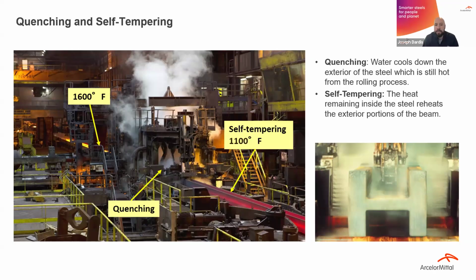So you can see it leaving the QST bank in that picture on the left, and it's dark all around that piece of steel. A few seconds later, it starts to glow orangish again. So what's happening is the heat retained within that core of that piece of steel then migrates back out to the surface. That's the self-tempering process, which brings a lot of ductility back into that shape. So you quench it, you get your increased yield, and then it self-tempers and removes a lot of that brittleness to give you a very high-strength material that still performs similar to our conventional steels as it relates to ductility.